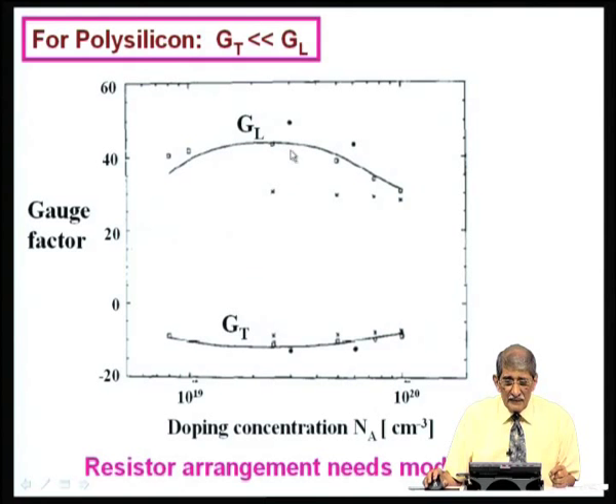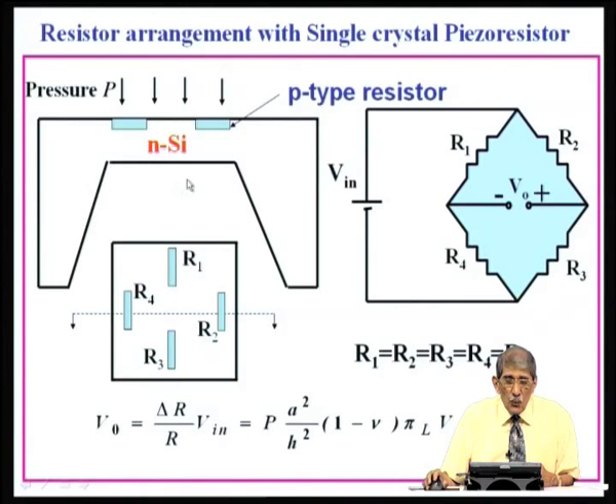We discussed this, you put them in the opposite arms of the bridge. Now, in the case of polycrystalline material, the gauge factor will be high, maybe about 30 to 40 in the longitudinal direction. In the transverse direction, it is something like minus 10, on an average about 10. So, you can't use the resistor arrangement that is used in single crystal. See, in single crystal, this is the membrane, this resistor is p type. You have arranged two perpendicular here, they will experience longitudinal strain, and these two you arranged parallel to the edge, they will experience transverse stress. So, delta R positive and delta R negative will be almost the same, and you will get very good sensitivity, because R1 and R3 will go up, R2 and R4 will go down, you get plus there, minus there. So, you get an output of delta R by R times input voltage, equal to V naught. That is what we have put here.